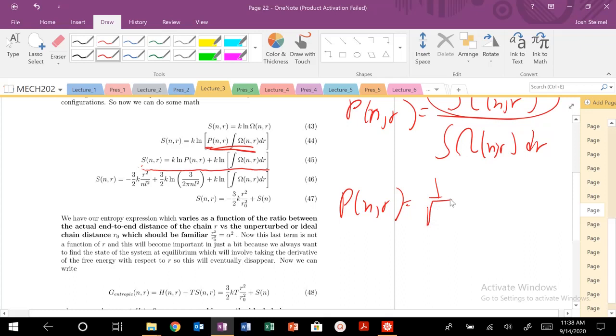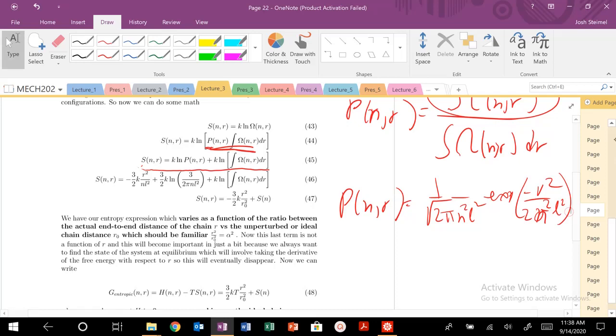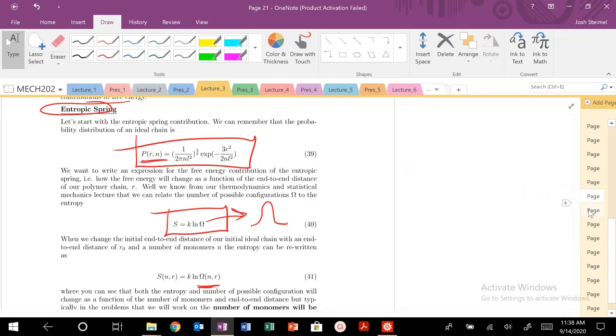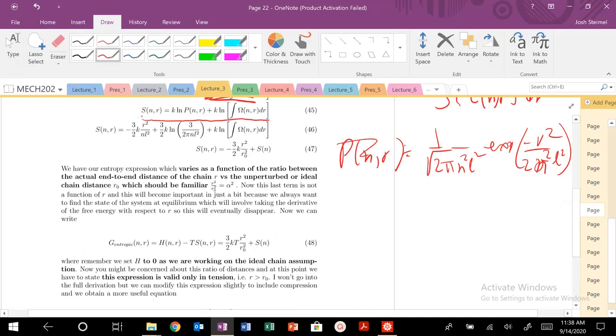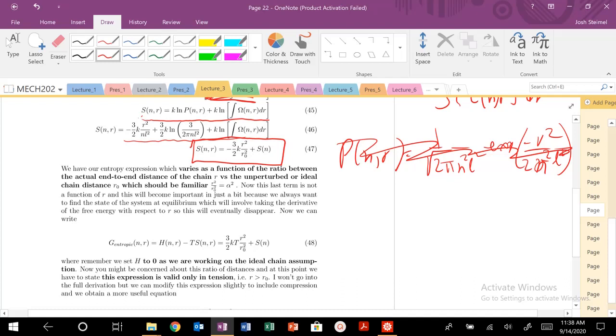Working with the expression involving the square root of 2π N l² exponential minus R² over 2N l² — with a factor of (3/2π)^(3/2) from the three-dimensional case — and simplifying, we get a very critical expression: entropy S(N, R) is a function of the number of monomers and R. It varies as a function of the ratio between the actual end-to-end distance R and R-naught, which is the end-to-end distance in the ideal chain: R-naught² = Nl².